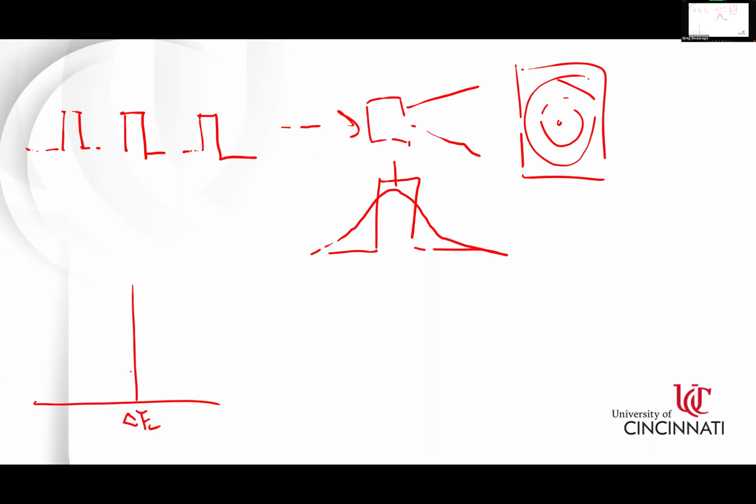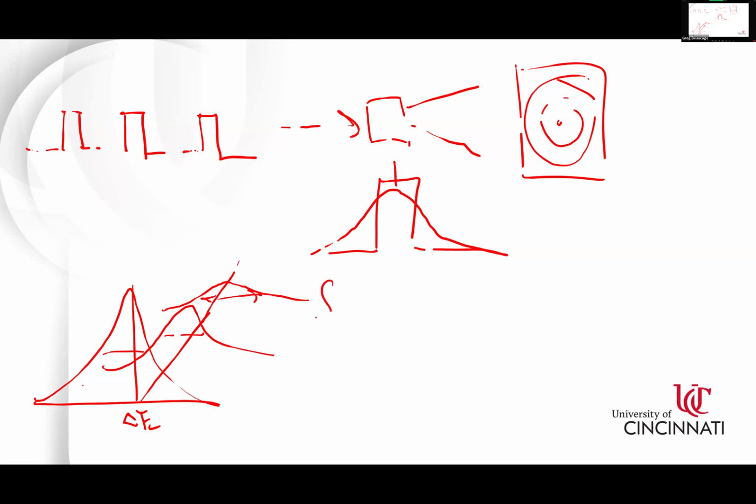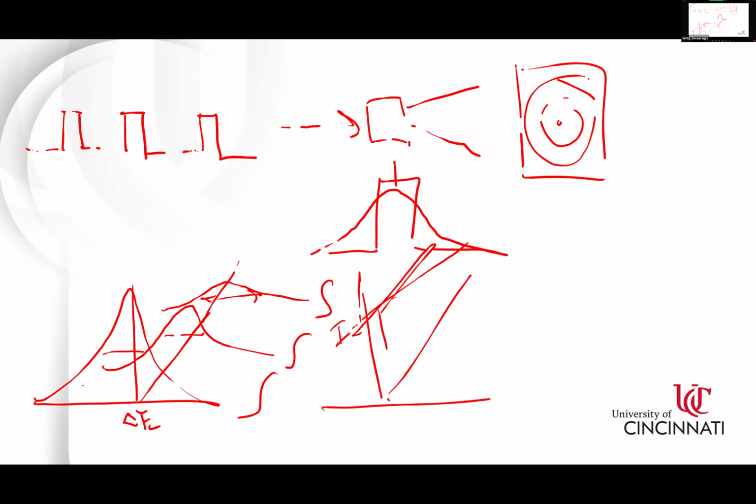And if I look at that as a function of energy transfer and Q, what you would see for the incoherent scattering is some dependence as you go to higher and higher Qs. This would broaden, assuming you have some diffusional motion, and the full width at half max would broaden. But the integral of these, if you integrated all of these in the same chart, would be a constant, if this was the incoherent scattering, right? That integrated quantity is a constant. But the shape of it will distribute wider and wider as you have energy transfers over shorter distances, right? Over shorter distances, it is more probable that your particle has left that volume.